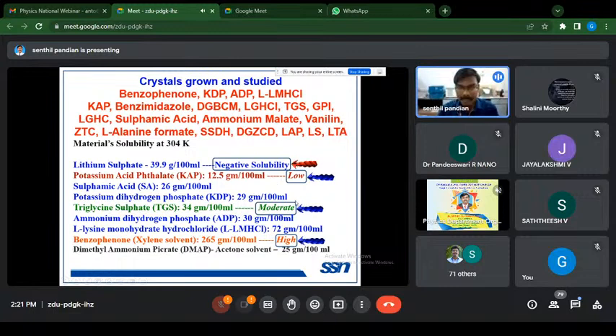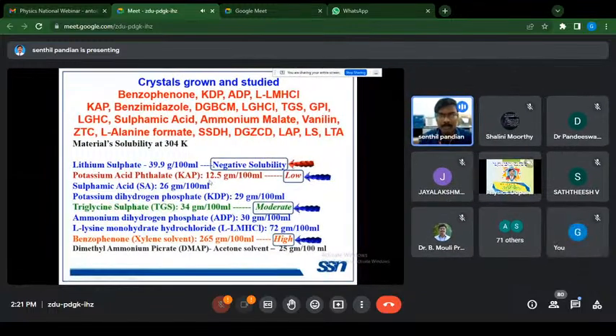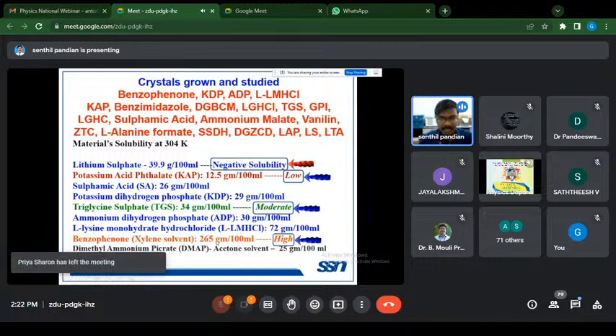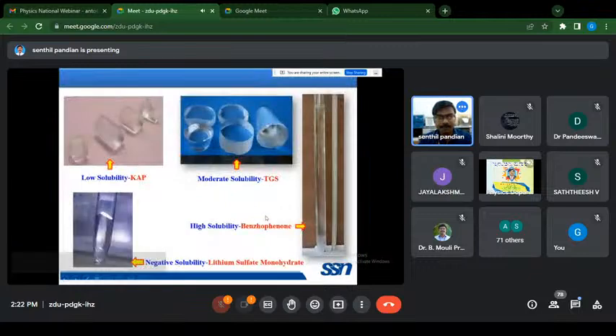So we have successfully grown positive soluble materials like this and a negative soluble material like lithium sulfate. You see the low soluble KAP at 12.5 gram per 100 ml, then moderately soluble triglycine sulfate at 34 gram per 100 ml. You see the highly soluble material at 265 gram per 100 ml, benzophenone, using xylene as a solvent. So all these kinds of crystals are possible by this SR method. This is the low soluble KAP, and this is the moderately soluble TGS. This is the highly soluble benzophenone single crystal. This is the negative soluble lithium sulfate single crystal.